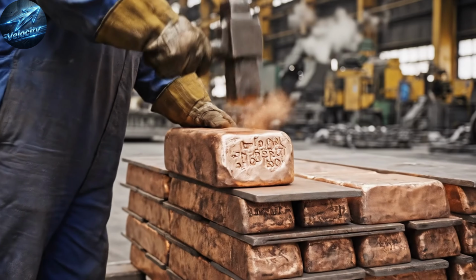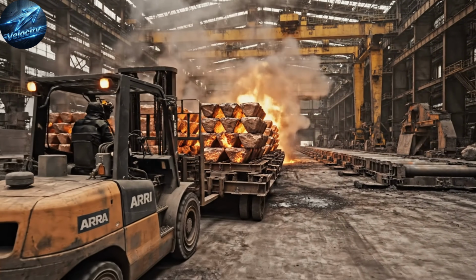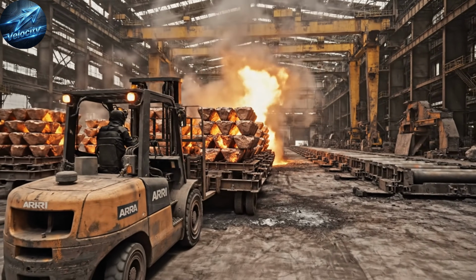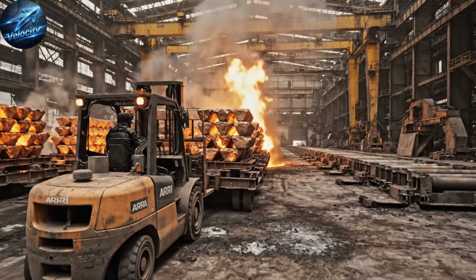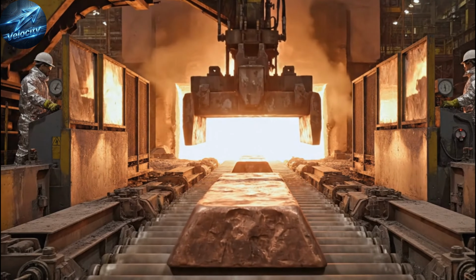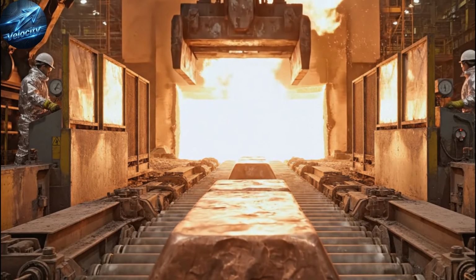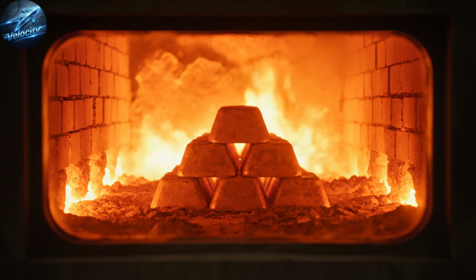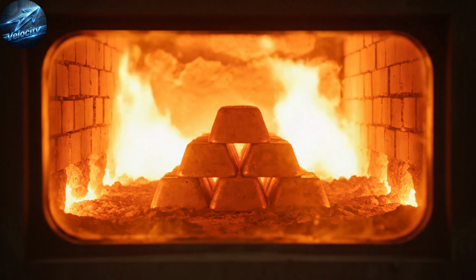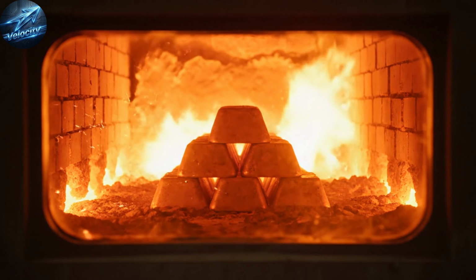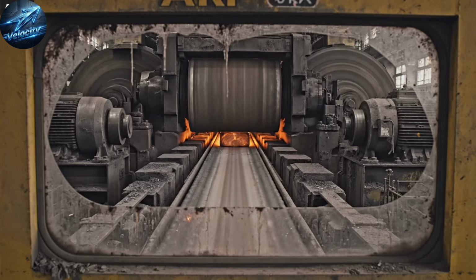Ingots don't become sheets by magic. Reheat too low, edges crack. Too high, oxide grows thick and ruins surface. Rough rolling hits hard, then pass after pass controls thickness without tearing. When the sheet work hardens, they anneal to restore ductility. The final checks are brutal. Thickness, flatness, surface quality. Because if the sheet is wrong, the giant pot will warp later.